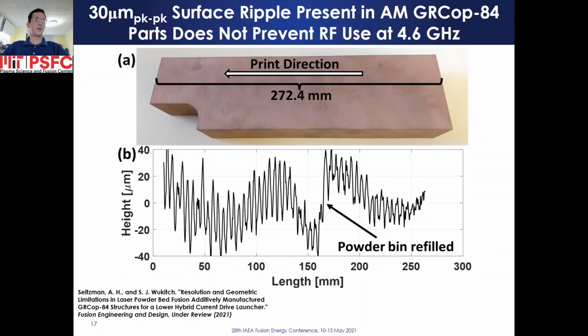A 30-micron peak-to-peak surface ripple present in additively manufactured GRCop-84 due to the finite stability of the LPBF printer does not affect RF use at 4.6 GHz. A small knit line is present on the surfaces of parts where prints are paused to refill the powder bin.